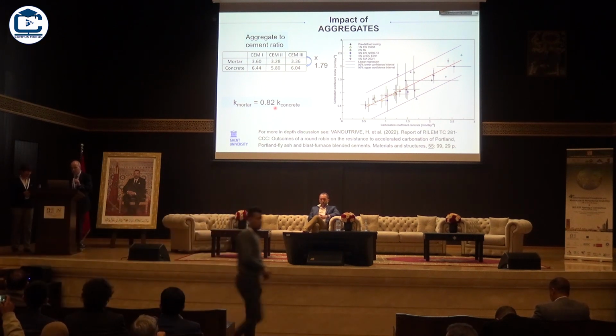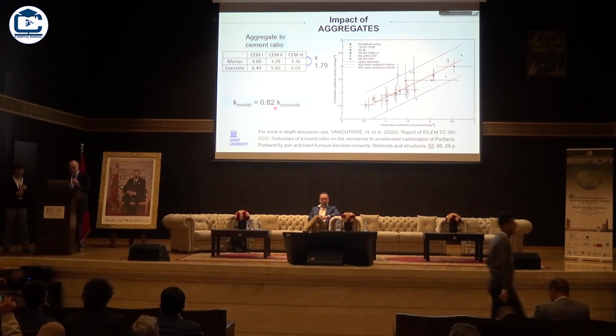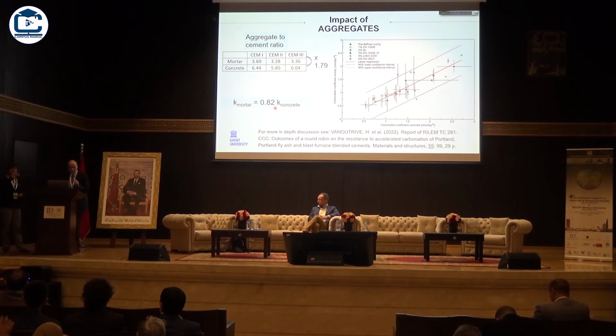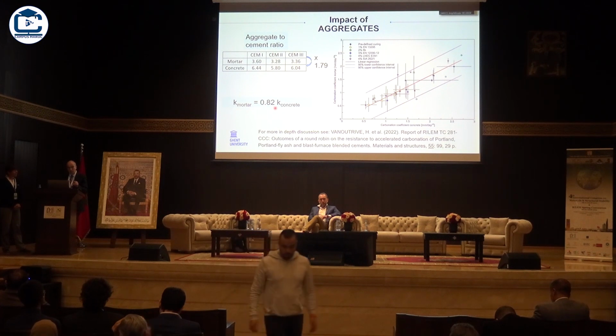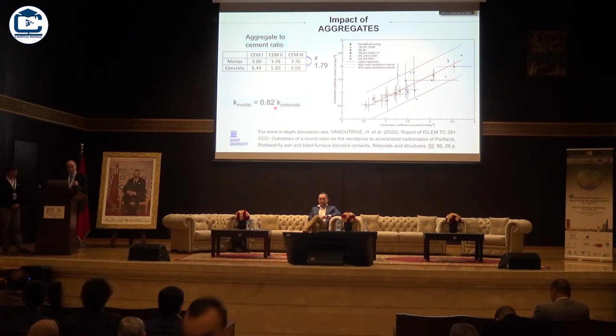Thank you very much. Really, it's a very interesting presentation. We understand really about carbonation. As you know, the most important thing besides strength is durability. The bottom line regarding our infrastructure is that deterioration is mostly due to corrosion coming from chloride and carbonation, and we can see the great importance of carbonation. The specific material and also the standard test are very important. Curing is also very important. If you pay attention, then you can improve the problem of carbonation.